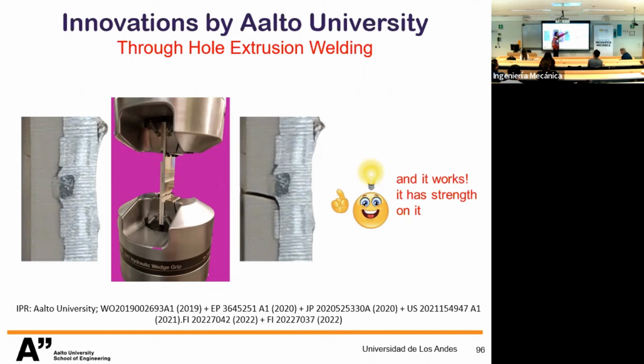So extremely strong joints. But the temperature for material flow of aluminum is about 400 degrees. Okay? The aluminum behaves like this. We are able to deform it and close the surface in three-dimensional flow, okay, at 350, 400 degrees. And this melts at 120, and at 180 is vaporized. So how can we produce this?